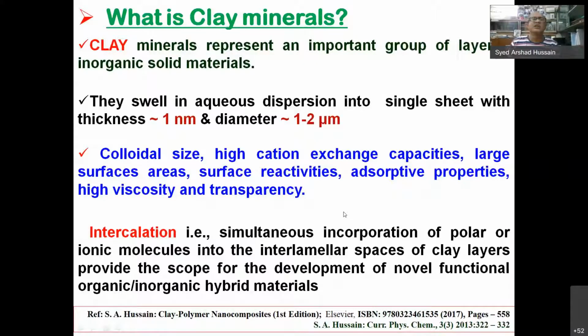So what is clay? Clay minerals represent an important group of layered inorganic solid materials. They swell in aqueous dispersion into single sheets of thickness of the order of 1 nanometer and diameter of micrometer order. They have colloidal size, high cation exchange capacities, large surface areas, adsorptive properties, and very high viscosity and transparency also. Another interesting property of clay is intercalation. That means one can simultaneously incorporate both polar as well as non-polar material within the clay system. So this gives the opportunity to use clay as a novel functional host material to prepare hybrid systems.